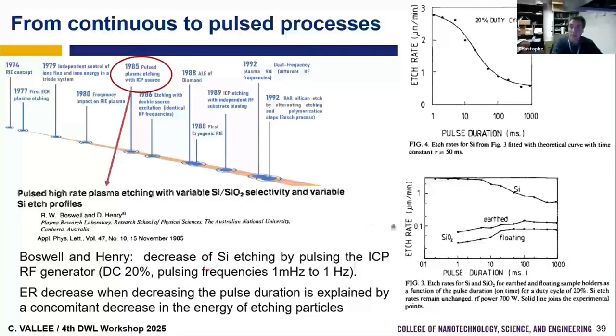And in this paper, they were pulsing the ICP generator, from 1 millihertz to 1 hertz, and the duty cycle was 20%. So 20% means that the plasma is on during 20% of the period. So if, for example, the pulse duration is 1 millisecond, 20% means that during 0.2 millisecond, we apply the power, and during 0.8 millisecond, we don't apply any power.